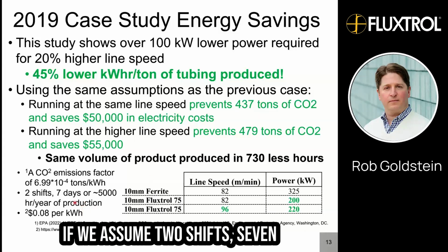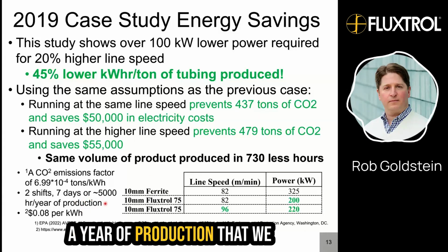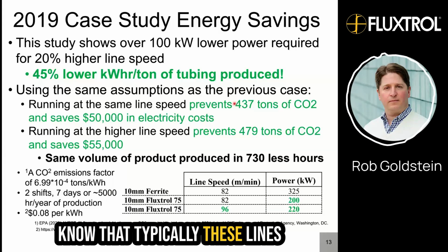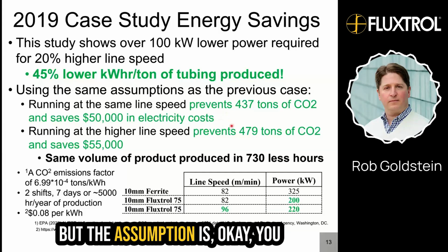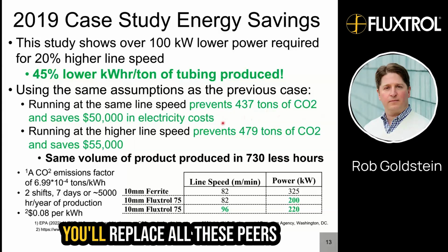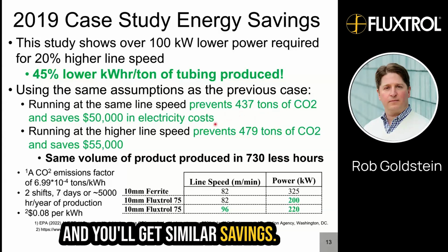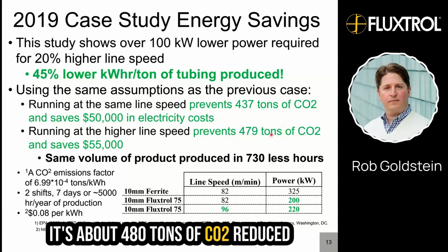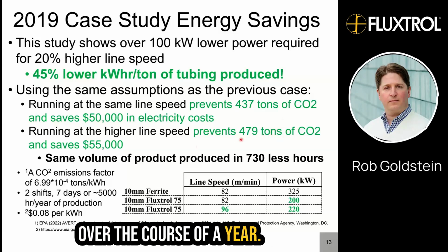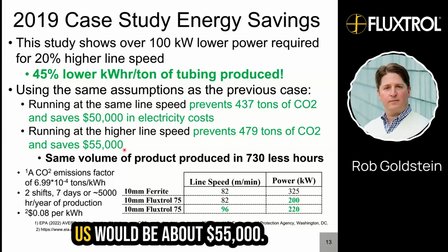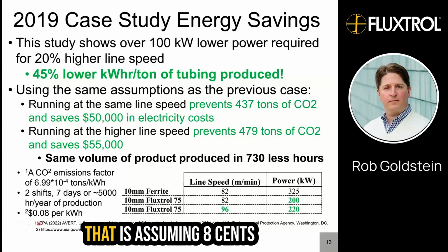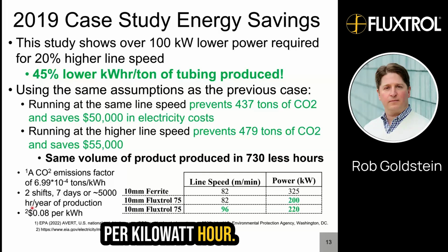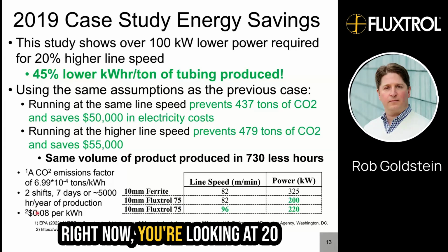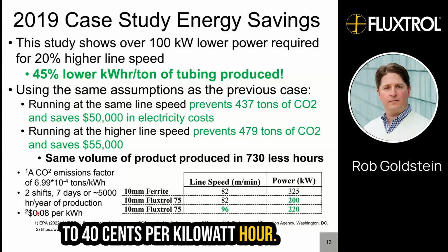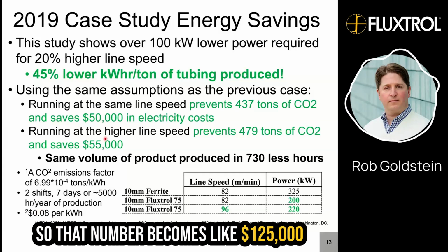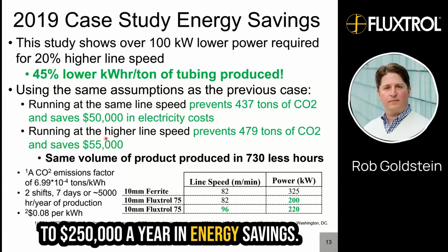If we assume 2 shifts, 7 days a week, about 5,000 hours a year of production, we know that typically these lines will not run that single product, but the assumption is that across the family of products, you'll replace all these impeders and you'll get similar savings. At the higher speed, it's about 480 tons of CO2 reduced over the course of a year. And your energy savings in the US would be about $55,000, assuming 8 cents per kilowatt hour. If you're looking at Europe right now, you're looking at 20 to 40 cents per kilowatt hour, so that number becomes like $125,000 to $250,000 a year in energy savings.